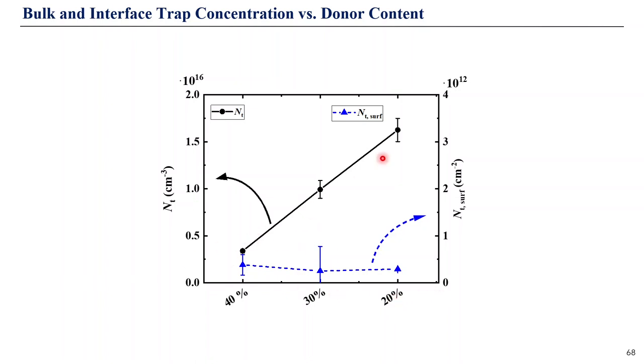That means that we do not provide any additional impurities in devices with lower donor concentration. And the origin for this increase in bulk trap concentrations comes from the not sufficiently developed interpenetrated network of donor material because of lower concentration, and formation of isolated donor islands within the bulk heterojunction, which act as morphological traps. So this conclusion is supported by additional measurements of TEM, photoconductive AFM, and GIWAXS.